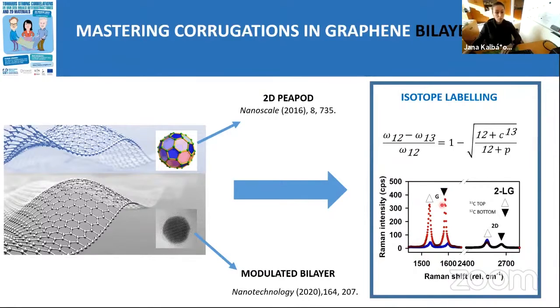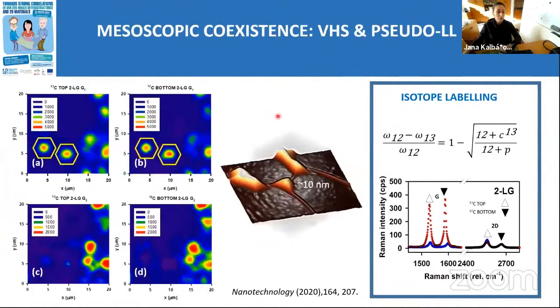Now let's have a look at what happens if we try to map the sample. So we scan over the sample, which is composed of two isotopically labeled graphene layers, and they are locally glued by particles, for example.